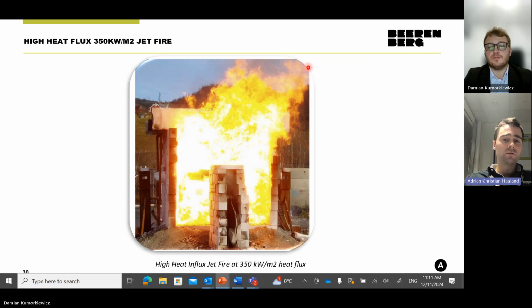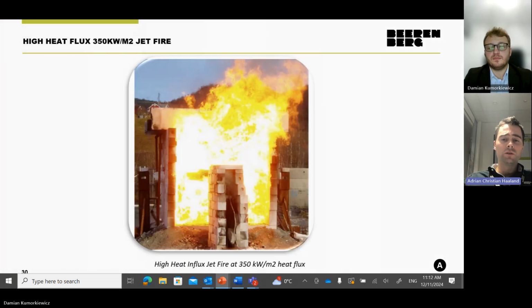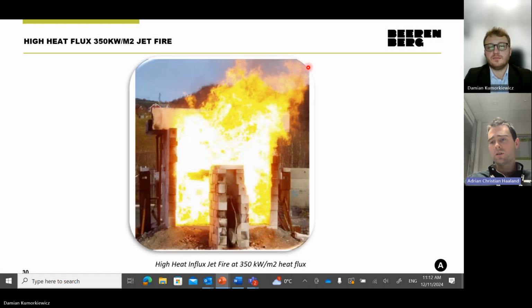And it is vastly different from a standard jet fire. In a high heat flux, you can pass 2 hours for a system. You put it into a high heat flux, you can fail after 10 minutes because everything falls apart due to the high temperature. So it is quite different, and you can't interchange the two methods. You can state that 350 can cover a 250 because it's so much more severe, but you can never look at a 2 hour or 1 hour standard jet fire and say, yeah, it probably does half an hour or a little bit more of high heat flux. You need to test it to see.